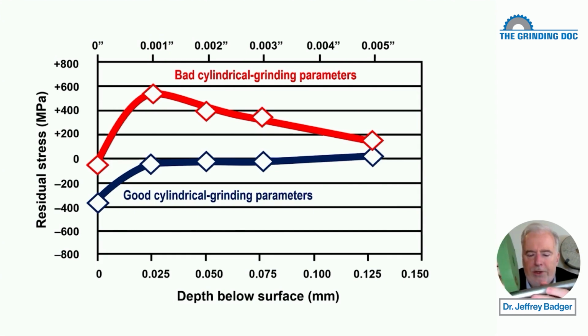They were traversing really slow with a really fast RPM. And I said, no. Here's what we're going to do. During traverse grinding, during rough grinding, we're going to use 90% of the wheel. We're going to have an overlap ratio close to 1, and we're going to remove most of the material. We're going to slow down that workpiece RPM. We're going to take a smaller cut, but we're going to traverse faster.